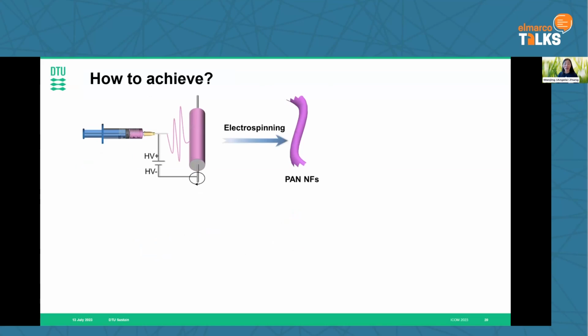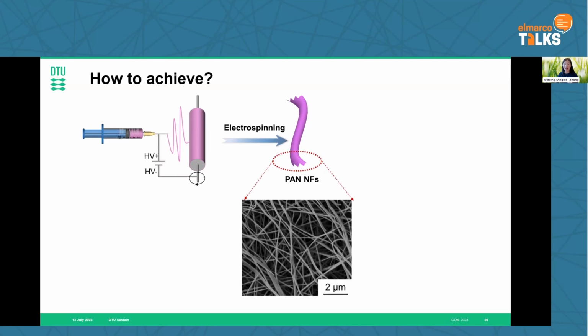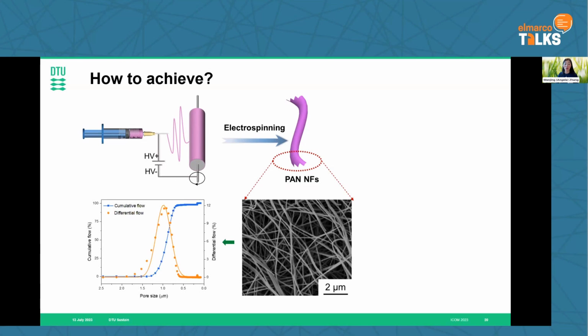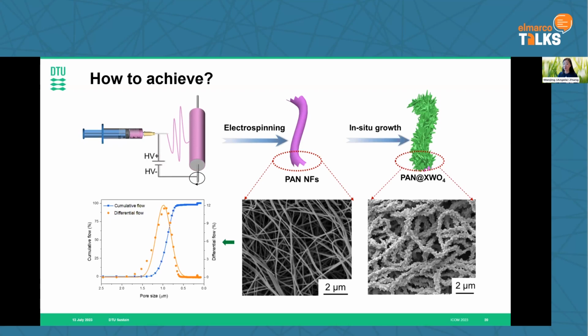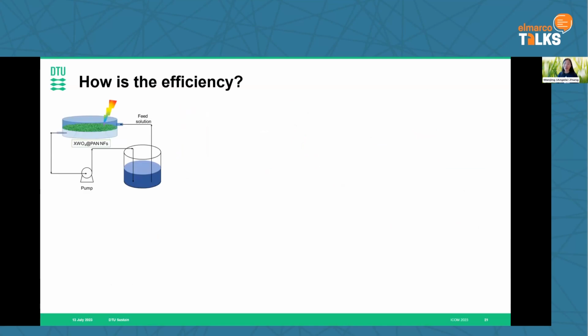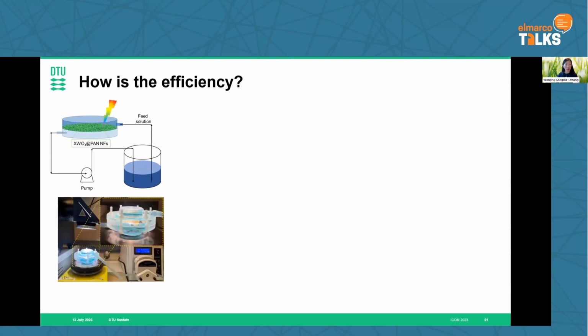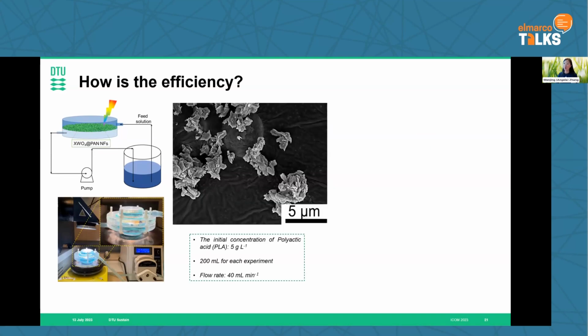So how do we do it? Always start with electrospinning. So this is a conventional nanofiber membrane, with a pore size of around 1 micrometer, like the microfiltration range. And then we do the in situ growth of those catalysts. So you can see after those reactions, all the fibers are roughened by our high entropy catalyst. Then we put it into our small reactors to evaluate the performance. We also have the solar light simulator to shine light on top of that. So you can see our small device, and the microplastic we use in our experiment is PLA.